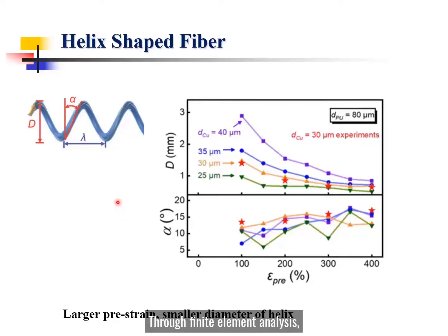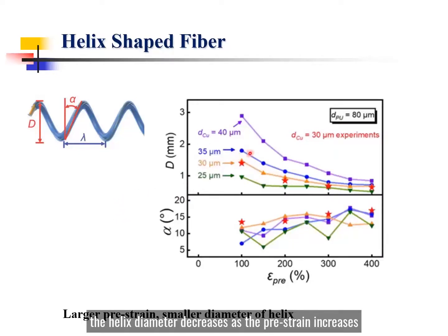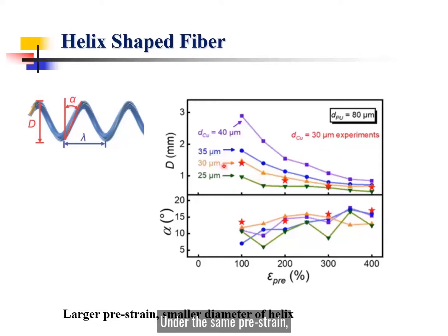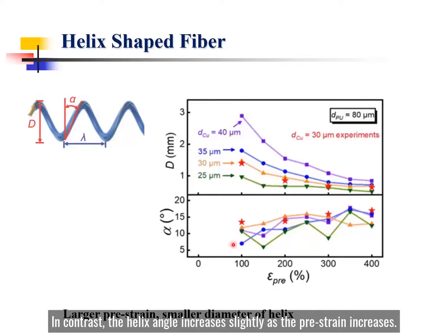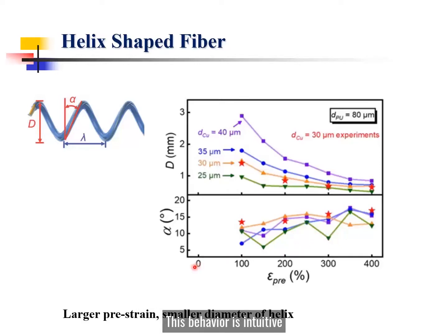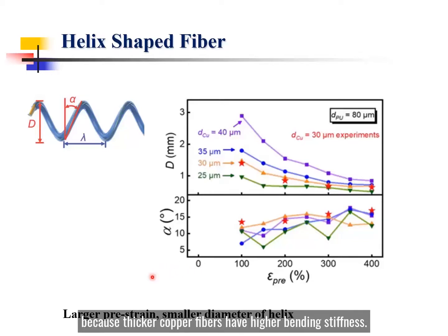Through finite element analysis, the helix diameter decreases as pre-strain increases for the different copper and PU fiber diameters. Under the same pre-strain, thicker copper fibers lead to larger helix diameters. In contrast, the helix angle increases slightly as pre-strain increases. The behavior is intuitive because thicker copper fibers have higher bending stiffness.